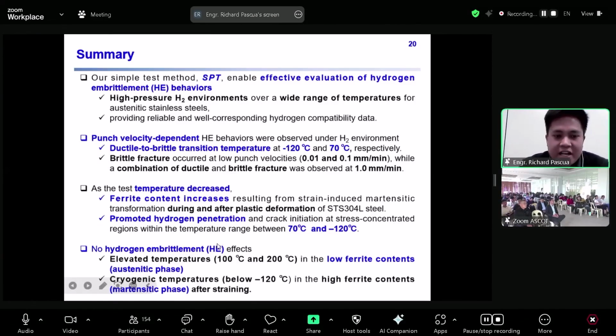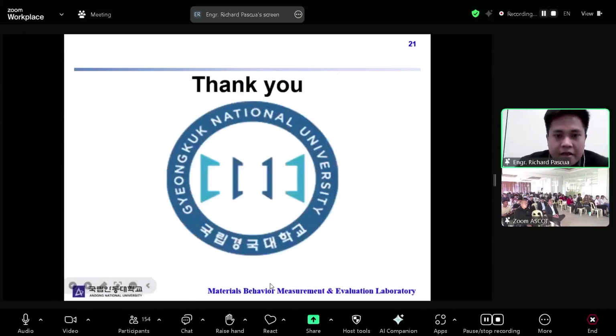And if this material is exposed at elevated temperature over 100 degrees Celsius with lower ferrite contents, and cryogenic temperature below negative 120 degrees Celsius with high ferrite contents or martensitic phase after straining, it could not provide hydrogen embrittlement effects in the materials. Therefore, we conclude that the stainless steel can be applied in a hydrogen environment at higher temperature over 100 degrees Celsius and at cryogenic temperature below negative 120 degrees Celsius. That would be all. Thank you.